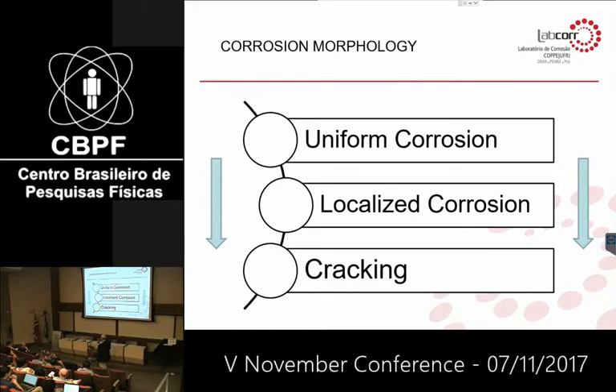I did not mention it, but the possibility of heterogeneous conditions along the axis of the pipeline is very important, due to the partial ingress of water and the existence of trapped gas or air. So it makes the situation a little bit more complicated. So what we need is to know the localized corrosion susceptibility of the material in the most precise environment.